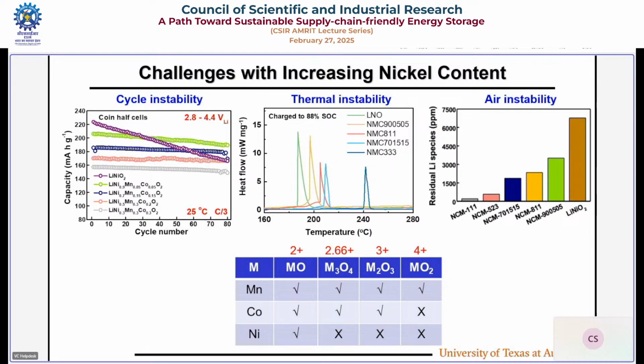To me, it's not strange. If you take manganese, all these oxides are known. MnO, Mn3O4, Mn2O3, MnO2, no problem. So I know manganese 3 plus is stable. Manganese 4 plus is also stable. If you take cobalt, we have CoO, Co3O4, Co2O3, there is no CoO2. Okay, reasonable. Nickel, we have only NiO. There is no Ni2O3, there is no Ni3O4, there is no NiO2. That already tells me nickel 3 plus is not stable. That's why you have this residual lithium. So you can understand all these from very basic things.